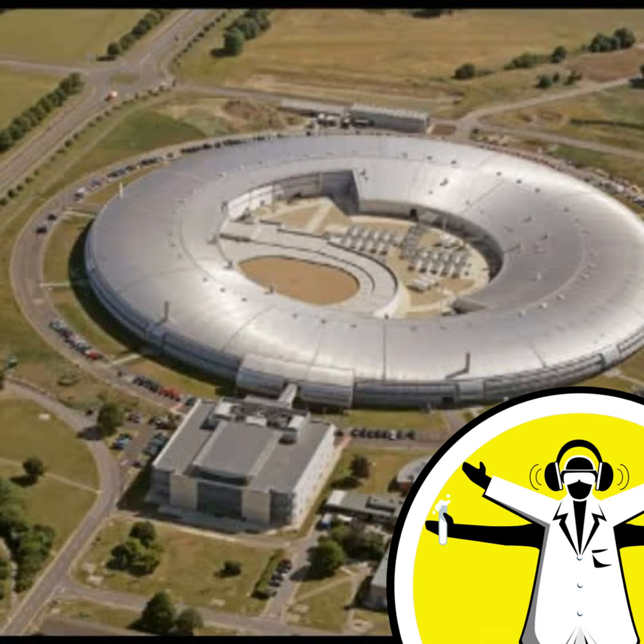In terms of where you get it, in nature it's extremely rare. Because it contains this iron 2 component, it's very sensitive to air oxidation, and so it's very difficult to find. When I say it's rare to find, it's because it's very difficult to characterise, because as soon as you dig it up, and you might dig in the soil and find some green patches, but they quickly turn brown. And this is one of the challenges of studying this phase, because it's very air sensitive, that to actually study it we have to mimic the conditions where it occurs in very low oxygen levels, and that's what we've been doing on the synchrotron.